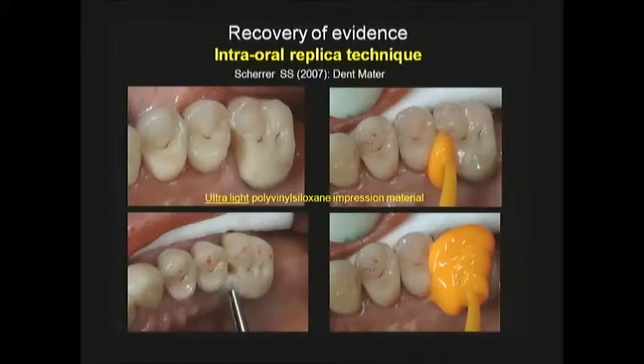You have to use anything else that is polyvinyl siloxane or silicone material, but you have to figure out which one. It depends on the reaction with the epoxy. Better ultra light, because the light material will show you information, but the ultra light is better than the light material. It goes more into detail. You have to clean that surface the best you can without touching with a metal instrument. You have to use lots of water flow and spray dry it.